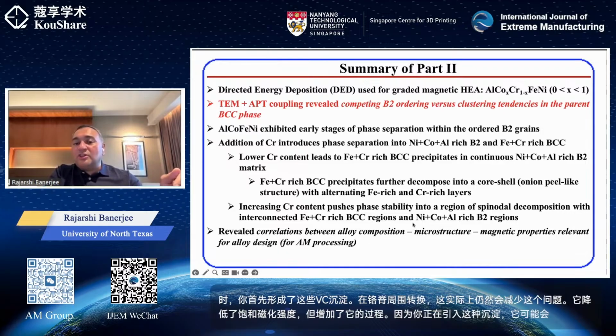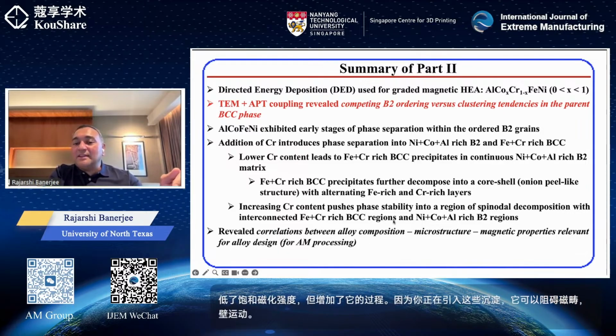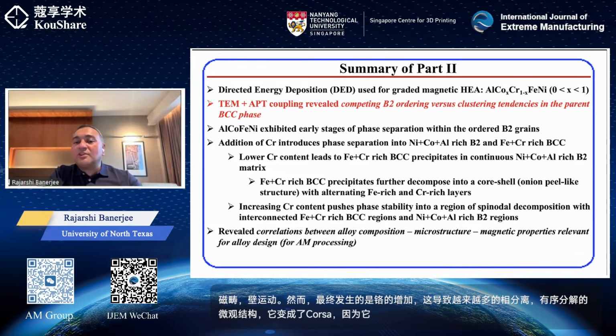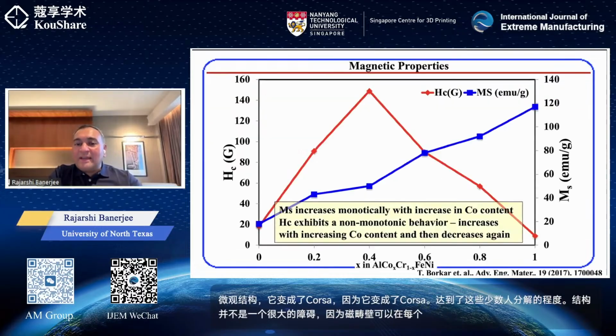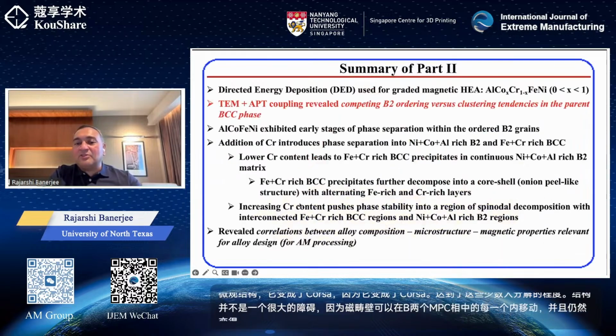And eventually, what's happening is that increasing chromium pushes it into a more and more phase-separated, spinodally decomposed microstructure, and it becomes coarser. As it becomes coarser, you reach a point where the spinodally decomposed microstructure is not as much of a barrier, because the magnetic domain walls can move within each of the B2 and BCC phases and become softer again in behavior, which is what the lower coercivity appears to be doing.